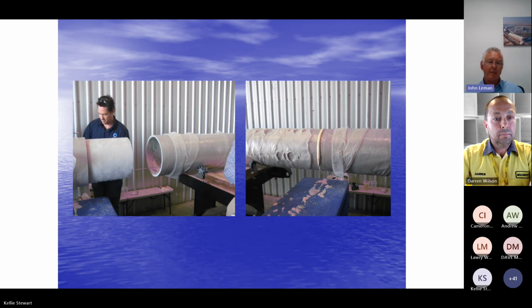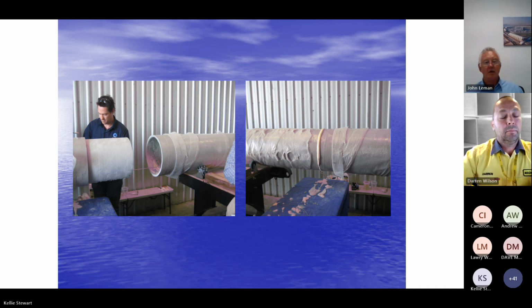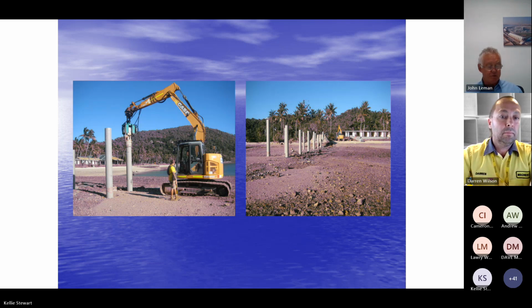Here's an example of the piles, the FRP piles that we used on this job, and just to show that you can quite easily do extensions to them. That's an extension done in a factory situation. This was one of the earliest jetties to have fiberglass piles in Australia, so we were quite interested in how the pile installation would go. For the upper part where we couldn't get the piling barge in because it was too shallow, the piles were put in by vibrating hammer. We used a fairly lightweight excavator because it's on an island and they don't have availability of a lot of big gear, but they worked really well, vibrating them in.